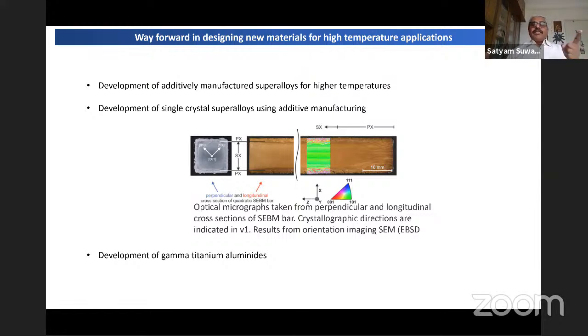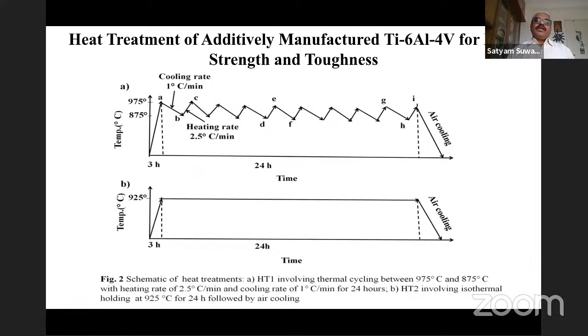And of course, gamma titanium aluminide, which always appears and disappears because of its poor fabricability. Here we have an opportunity to optimize the process and make engine components of gamma titanium aluminides, because the poor plasticity, which is an impeding factor for fabrication, is no more an issue for gamma titanium aluminide. The only thing is microstructural control, property control is the important thing.